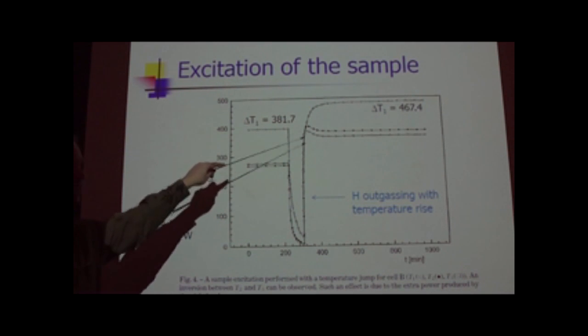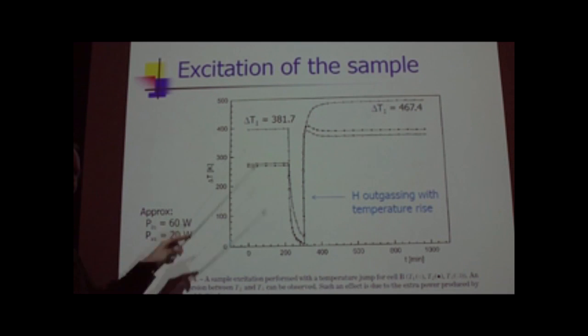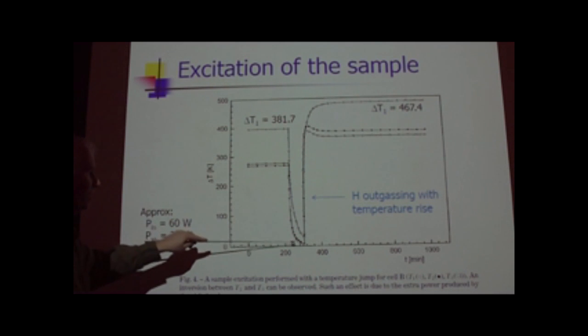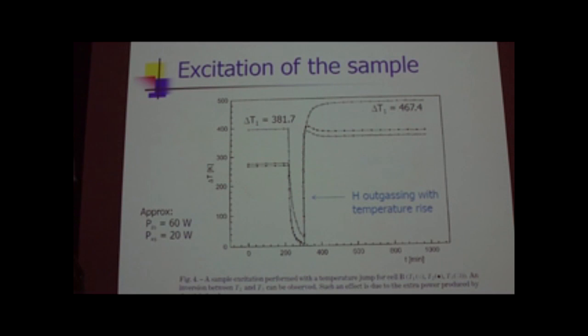Well, what the heck is this temperature cycling doing? If you like, you drop the temperature, you bring in more hydrogen for the vacancies, for the Fukai phase. For the part that's not in the Fukai phase, you actually just send it out. So you change the loading, and then you change it back to what it was before. So what the palladium hydride has to do is breathe out and breathe in, which means this temperature cycling is inducing a hydrogen flux. Deuterium flux in palladium deuteride kicks on excess heat, and in some cases it kicks on and sticks on for a while.